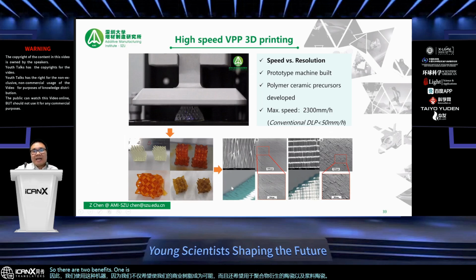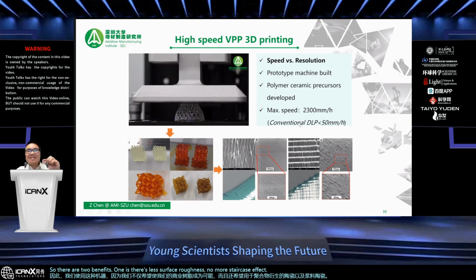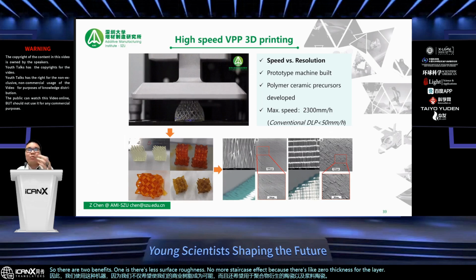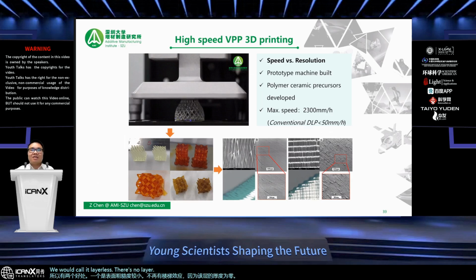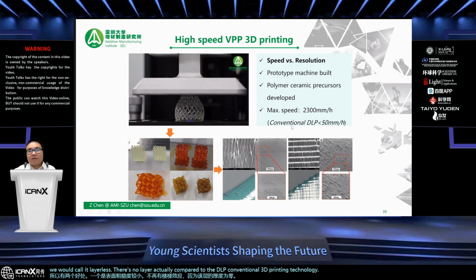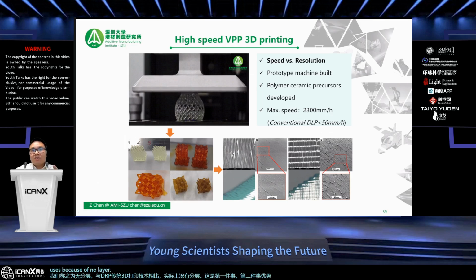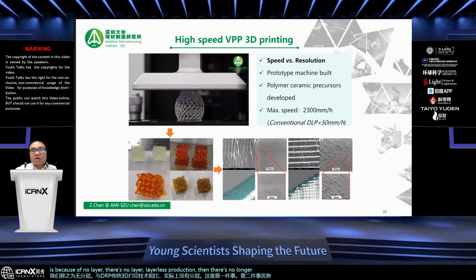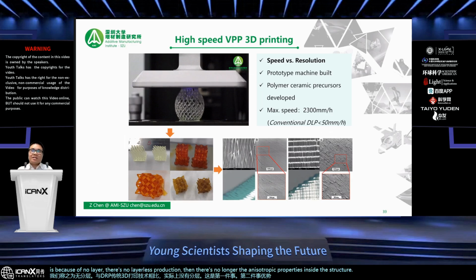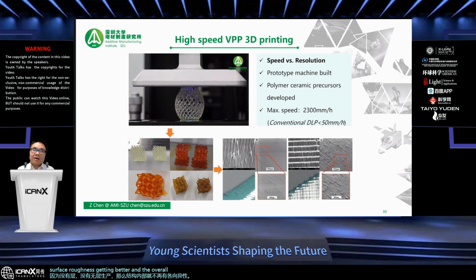One is there's less surface roughness. No more staircase effect, because there's zero thickness for the layer. This we would call layerless. There's no layer actually, compared to conventional DLP 3D printing technology. And this is the first thing. And the second advantage is that because there's no layer, there are no longer anisotropic properties inside the structure. So the surface roughness gets better, and the structure is overall isotropic.